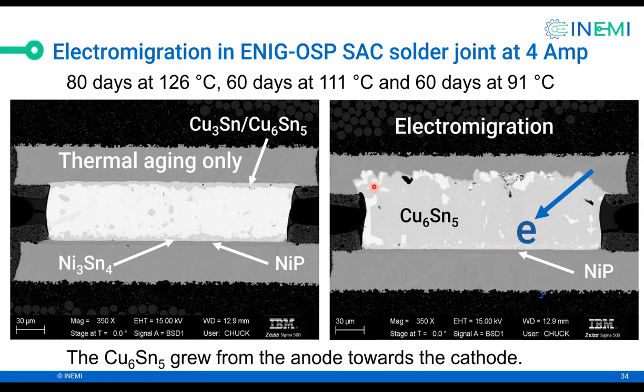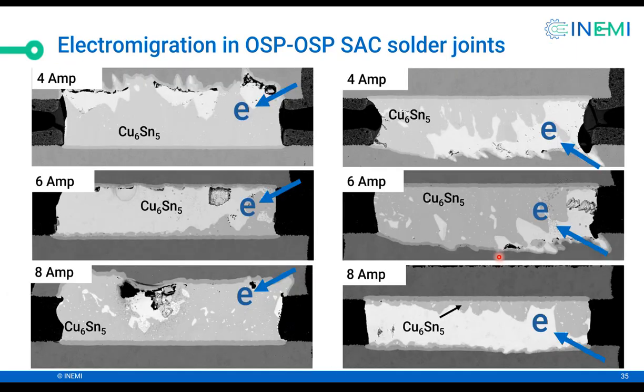So you can see the copper metallization dissolved into the solder, and the solder is mostly Cu6Sn5. And Cu6Sn5 has somewhat higher resistivity compared to tin. That's why the resistance goes up. Now here's a composite. So let me explain this.